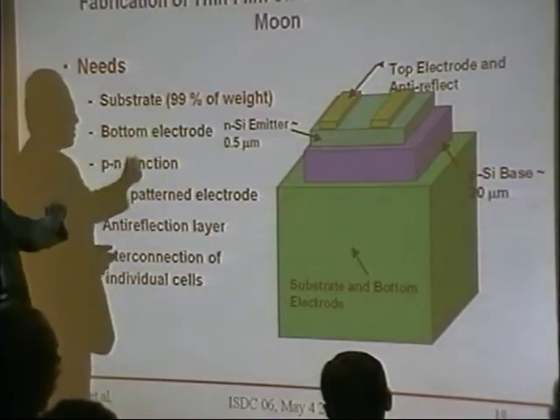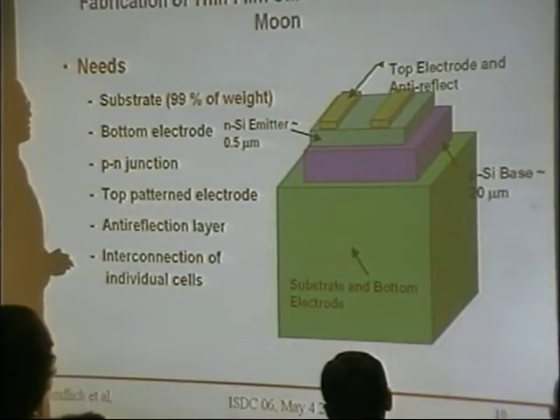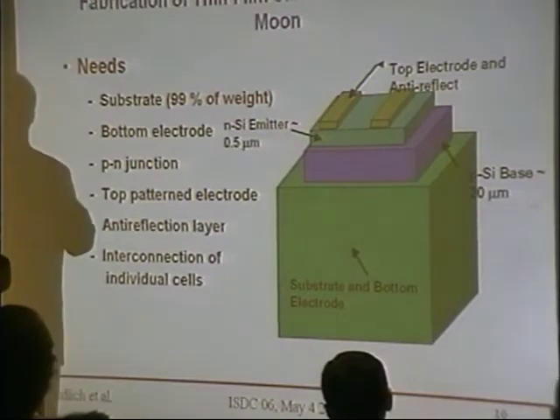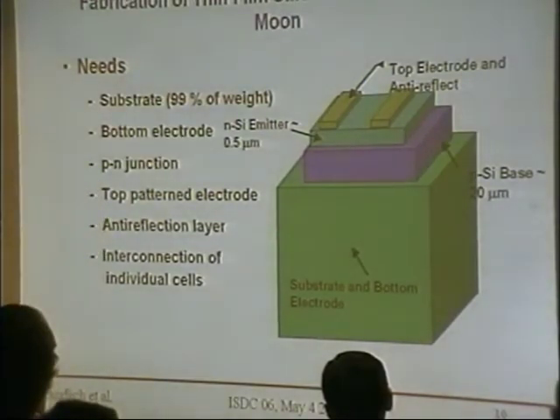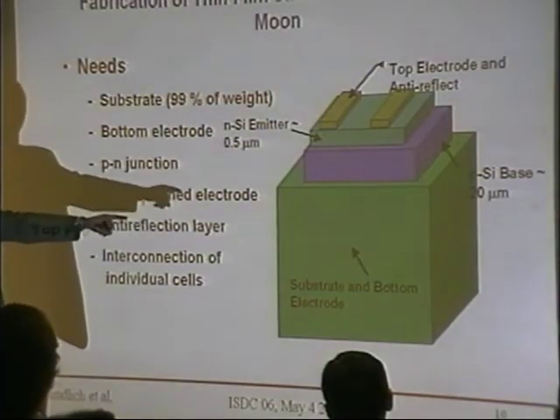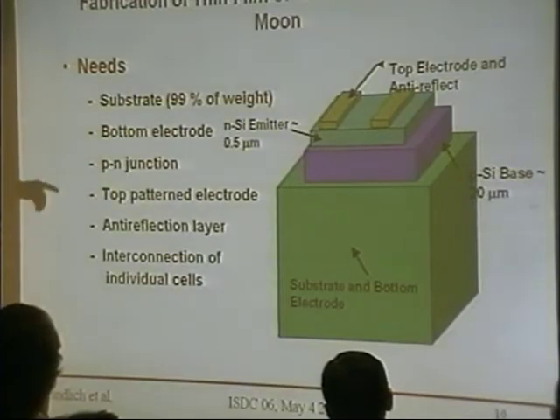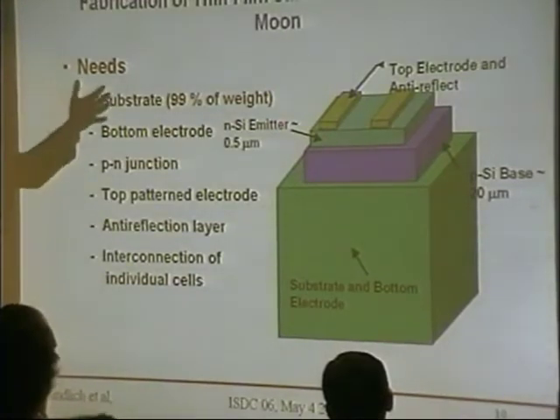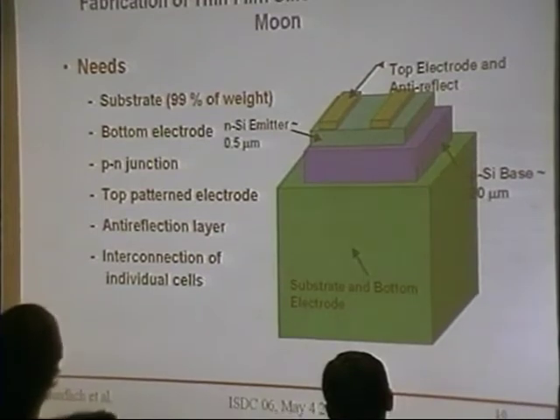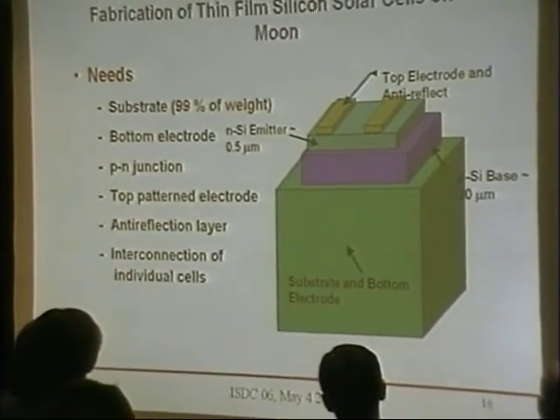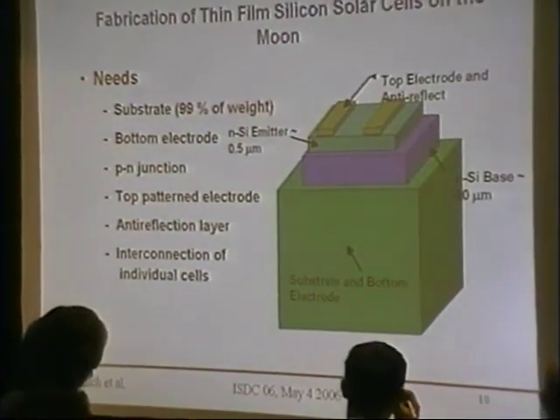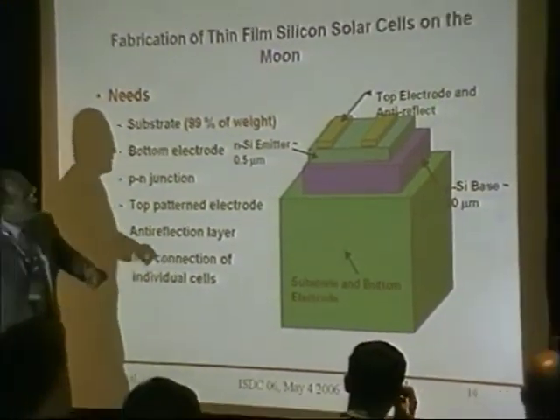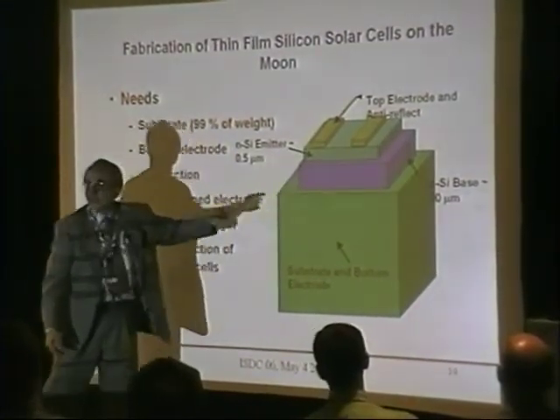And there are then electrodes at the bottom and at the front, a layer that's called anti-reflect. Most semiconductors are very reflective. They have a reflective surface. One will use an anti-reflect coating to harvest the light better. And then there is a very big guy, and actually it's really not at the right dimension: a substrate. In most thin film solar cells, the substrate represents pretty much 99% of the weight of the solar cell. In most solar cell systems, the ones that you see on the space station, in addition to that electronic substrate, there is also probably a honeycomb structure holding it. So the first big parameter, if weight is an issue, is to solve this substrate.